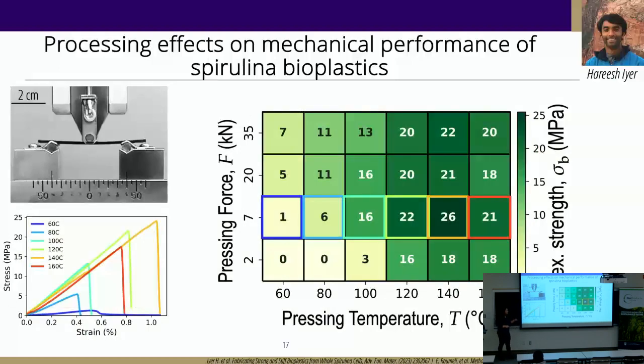Then, if we want to look at a 2D plot of changing temperature and pressure, here we're going to keep time fixed at 5 minutes, and now we're sweeping a different temperature profile in combination with pressure. And the numbers that you see over here correspond to the values of flexural strength. So I'm not showing you all the data. We have one representative stress strain curve for each of the temperature conditions so that you can see how rigid the materials are. These are very, very brittle. But you see that we are mapping here our flexural strength, and even if we look at a specific row where we are keeping our pressure fixed, you see the effects of temperature where we have variability about 26 times. We can go from 1 MPa to 26 MPa just by changing the temperature between 60 and 160 degrees by keeping the time and the pressure the same.